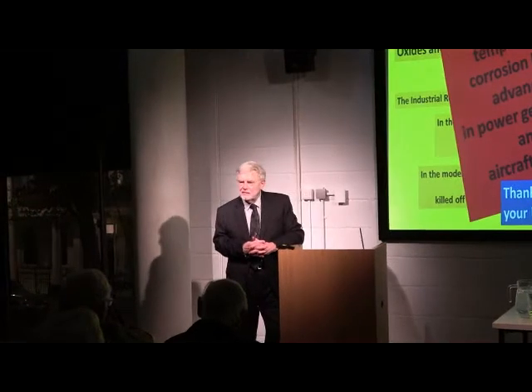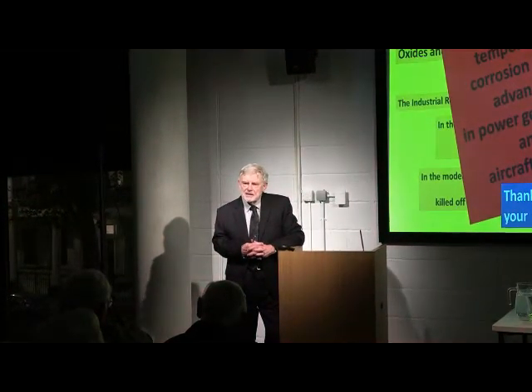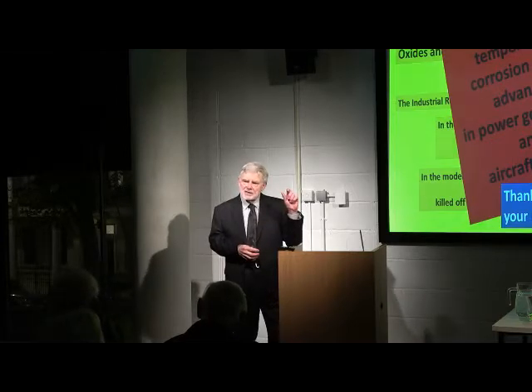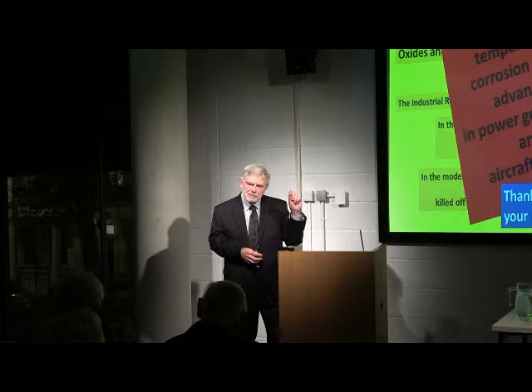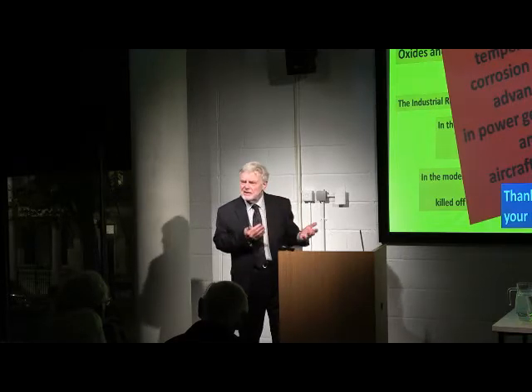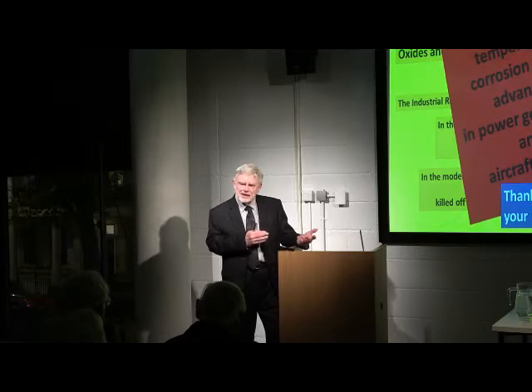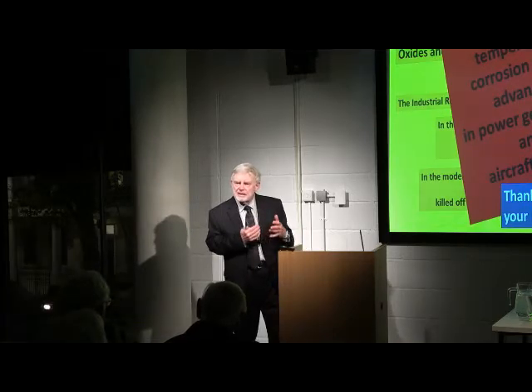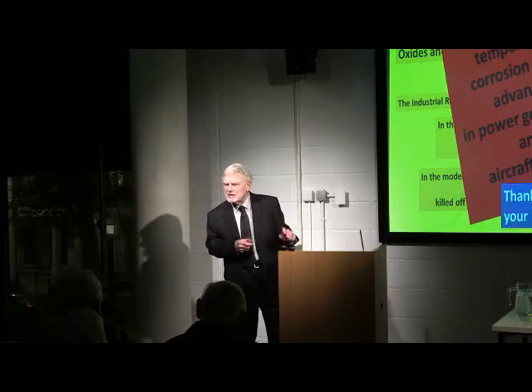Now, you've talked about high temperature corrosion limits, but at what temperature does corrosion start? Could it start at very low temperatures? With mild steel, it begins at around 450 degrees. By the time you've reached 550, there is a problem, particularly with mild steels, that the oxide changes from a reasonably protective form up to 550, and then thermodynamics turns it into another type of oxide called wustite, FeO, which is much inferior to the lower temperature form.